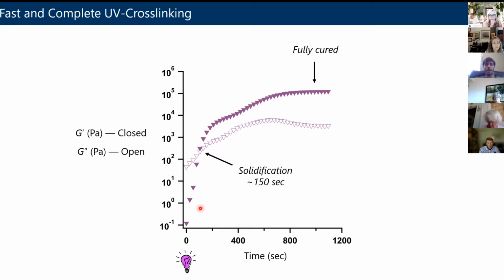So you start shining light on the material, and you can see that you pretty quickly have that G prime, the elastic contribution, jump up, and it becomes larger than G double prime, which is a characteristic of solidification. So after a couple minutes, 2 or 3, the sample transforms from a viscous liquid into a solid, and then you can see eventually these parameters stop changing. And that tells us that the reaction is complete. And we've got a nice elastomer out here.